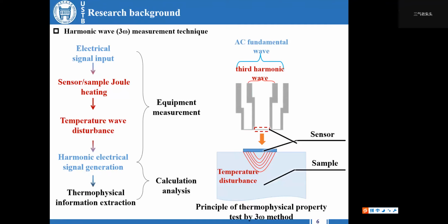The measurement principle of the third harmonic method is to input a periodic alternating current with an angular frequency of 1 omega to the sensor. Due to the Joule effect, a heat flow with an angular frequency of 2 omega is generated, heating the sensor and sample, resulting in a temperature wave with an angular frequency of 2 omega. A current with angular frequency of 1 omega and a resistor with an angular frequency of 2 omega work together to produce a harmonic voltage with an angular frequency of 3 omega.